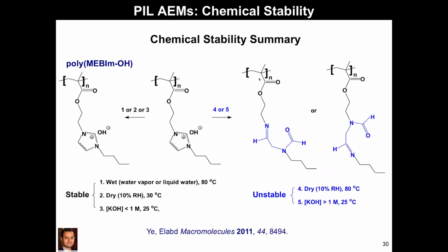And then we followed up and we did a lot of NMR on this, and we showed that under certain conditions, this is stable, but under other conditions, you can get it to be unstable, and you can see ring opening of the imidazolium, and also for this particular backbone, you can see some hydrolysis as well.